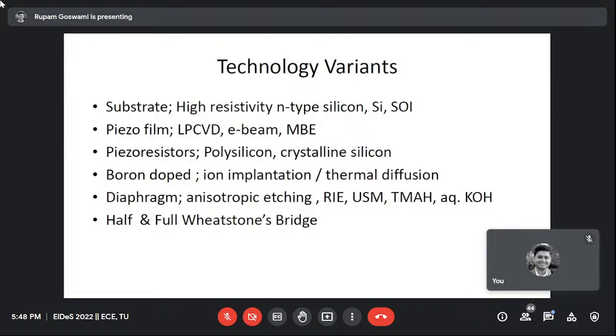So as we know, for piezoresistors we generally use either polysilicon or crystalline silicon. Crystalline silicon we use by making diffused resistors. Boron doping is done to enhance the piezoresistive coefficients. Phosphorus is not used in general. And when we talk about how to dope the boron, it is either ion implantation or thermal diffusion.